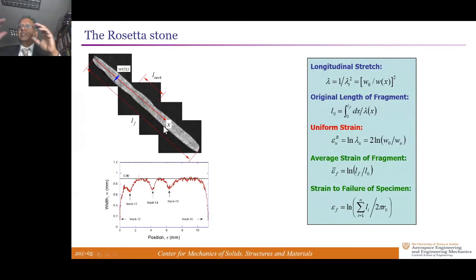I forgot to mention that at the outer periphery of our device, there was a very soft clay into which the specimen goes and launches itself and slows down. So we're able to recover those specimen pieces without damage. If you look at one of those, this is a fragment which broke at both ends through a fracture process. But along the length of that, you see the width is not uniform.